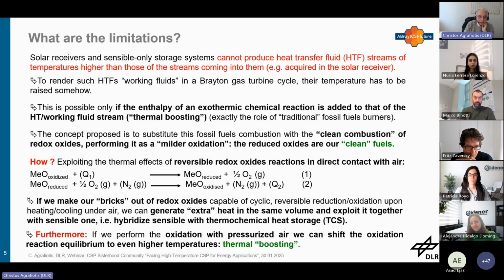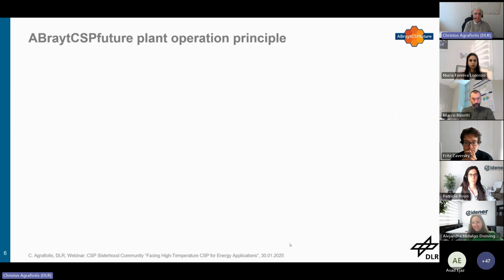redox oxide, so we can generate extra heat in the same volume and do hybridization of sensible with thermochemical storage. Furthermore, not only that, if we perform the oxidation with pressurized air instead of atmospheric air that was used for the reduction, we can shift the oxidation reaction equilibrium to higher temperatures. So the amount of heat we're going to get from the exothermic oxidation would be higher than that which we spent to reduce the oxide. And this is how we can hope to achieve thermal boosting, so to achieve an airstream of higher temperature than before. Of course, this is at the expense of pressurizing the air.